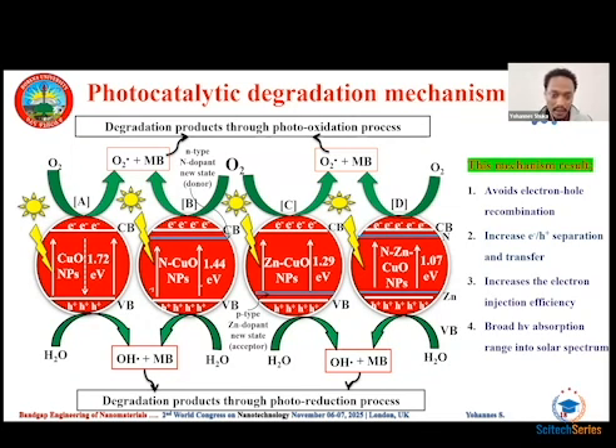In the same fashion, when we dope or modify the surface of copper oxide with nitrogen, its band gap is reduced to 1.44 electron volt, and when the hole produced at the valence band reacts with water in the same fashion, this radical reacts with methylene blue, leading to the photoreduction process. Modifying the surface with nitrogen leads to the formation of a new state, called the N-type nitrogen doped state, which is a donor state below the conduction band, resulting in a narrower band gap for the nitrogen doped copper oxide nanomaterial. In the same fashion, when we modify the surface of copper oxide with zinc, it leads to the formation of a new state above the valence band, and that narrows the band gap to 1.29.